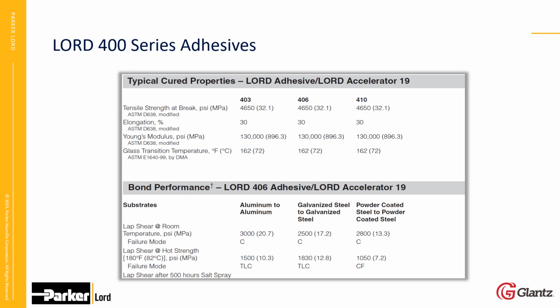Down below, you'll see the bond performance in the different substrates, where we see aluminum to aluminum at 3000 psi strength, galvanized steel to galvanized steel at 2500, and powder coated steel to powder coated steel at 2800. We're the only product that can go through the powder coating process, 450 degrees Fahrenheit for 30 seconds, and actually we come out stronger on the other end.